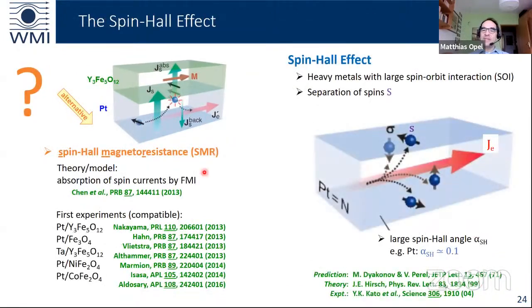So how does the spin-Hall magnetoresistance work? We have to consider the spin-Hall effect. Heavy metals with a large spin-orbit interaction show a spin-Hall effect. One of these heavy metals is our platinum. And the spin-Hall effect leads to a separation of spins whenever I drive a charge current, JE, through the platinum metal. So the spin up electrons are deflected to the right, the spin left electrons deflected to the top, the spin down electrons deflected to the left, and the spin right electrons deflected to the bottom. And it leads to a separation of spins, and the efficiency is given by the so-called spin Hall angle, which is about 0.1 in platinum.